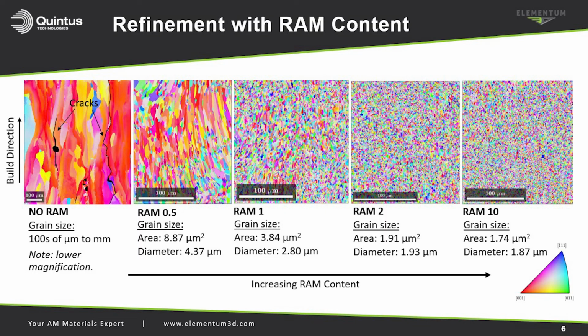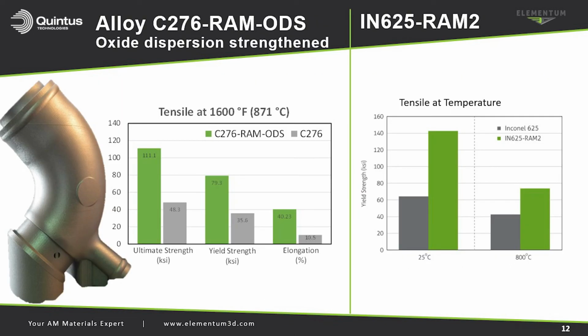So the RAM approach, as mentioned, there's a number of things that it can do. But one of those is it can provide inoculation sites that nucleate the grain growth of these alloys during solidification. That can form a relatively fine equiaxed microstructure with more isotropic properties, both in the growth and XY directions. So that's beneficial for predictable, uniform properties. And now you can control that microstructure through the subsequent heat treatments as well.